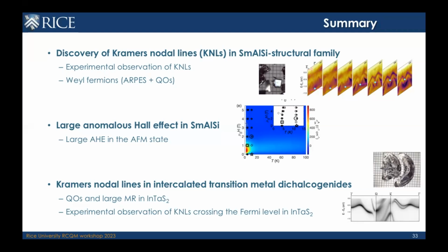In the samarium aluminum silicon, could there actually be a ferromagnetic component that gives rise to the anomaly? I didn't show all of the measurements that we have, but we have magnetization as a function of field, and there's nothing left. Typically, though, incommensurate magnetic scattering can potentially give a component that has a zero moment along a particular direction, which can potentially contribute.